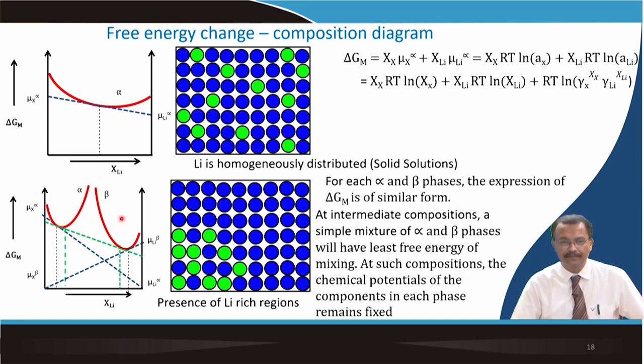del G minima here. Now, the important part here is that at any composition of lithium, if you can draw a tangent, then wherever it cuts the axis where lithium is maximum, that will give you the chemical potential of lithium. For the other phase, the chemical potential you can get from here. Same thing applies here. So, if you draw a tangent at this particular composition, it will come here. For this one, it will come here. And if you have a common tangent, that indicates that the phase mixture, they are having the minimum free energy condition. So, this is just the implication of the free energy change and composition diagram.